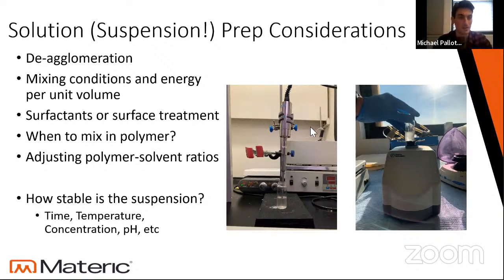When it comes to the mixing conditions and the energy per unit volume, that'll depend on what happens to the viscosity of your solution. In some cases, the vortex mixing and a magnetic stir bar will be enough given the solution viscosity even after additives are added. In some cases, we'll need to manually shake solutions. We'll have to use overhead mixers as well, just to make sure that those particles are dispersed correctly.